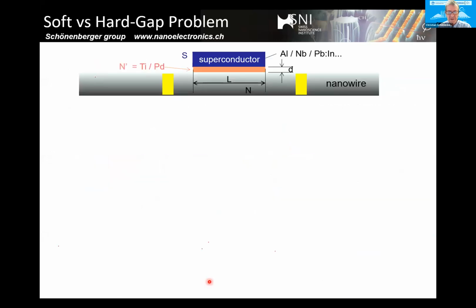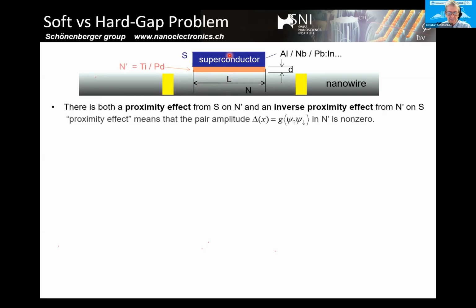Okay, so here's a sketch of how a Majorana nanowire could look when you evaporate the superconductor afterwards. Then you have a section of nanowire of some length, maybe a tunnel barrier, yellow, on the left, a tunnel barrier on the right, and we evaporate the superconductor using an adhesion layer like titanium and palladium. And then the problem is actually like this: you induce superconductivity first maybe in this adhesion layer, but this adhesion layer on its own can have an inverse proximity effect and suppress the gap in the region of the nanowire.